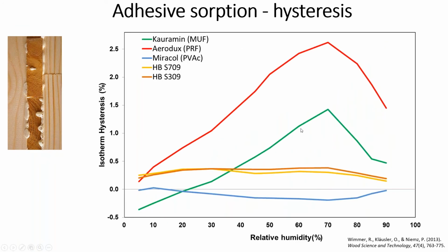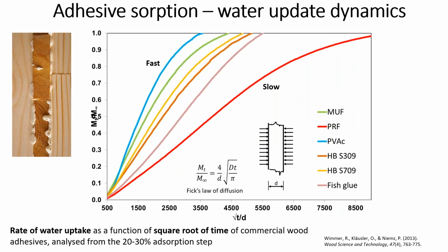This is the hysteresis, and you can sort out those which respond strongly, or are strongly different between absorption and desorption, where the others are weaker. And so you see here a great uptake in water and a strong hysteresis like with MUF and PRF, phenolic resorcinol formaldehyde. And then I applied the diffusion study, like the rate of water uptake using Fick's law of diffusion,